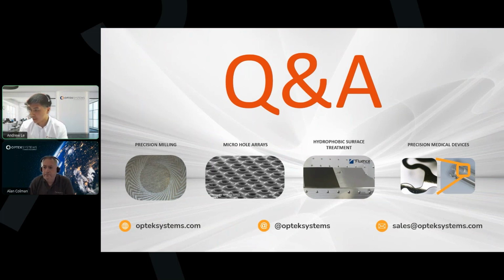This is something where a laser milled finish can consistently work these to about 200 nanometers in Rq roughness, which is a really strong advantage in comparison to a lot of CNC contact-based solutions, which on average seem to only get finishes of around 600 to 900 nanometers in roughness. What this allows us to do, if that's what our customer is asking for, is that we can create surface finishes that are ready for work right off of the laser bench. Brilliant. Thank you, Andrew.